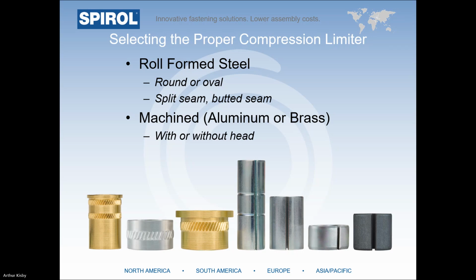Within the roll form steel category, we offer a circular shape with split seam for post-mold installation, or a butted seam for molding in. These are also offered with an oval shape to accommodate a wider tolerance in one axis for easier alignment, which is particularly useful when you're using multiple limiters in an assembly. Within the machine category, they can be installed either by pressing in or molding in. You don't need to specify a particular machine version to match the installation method.